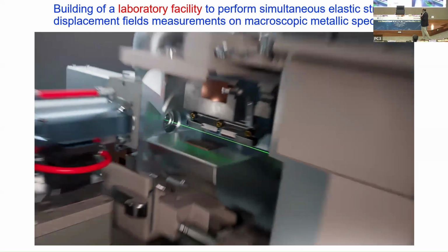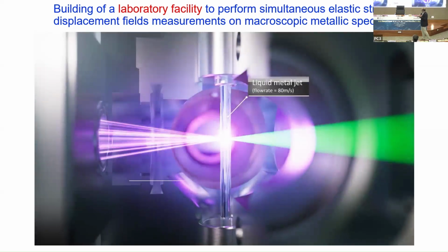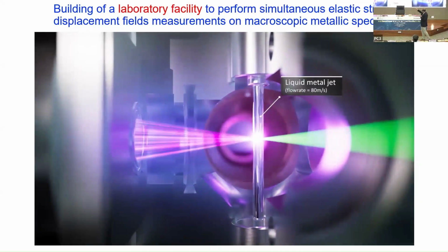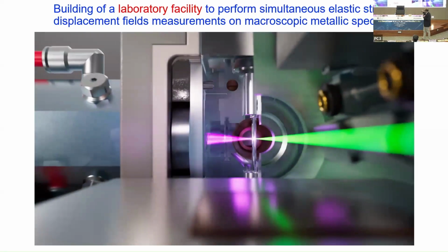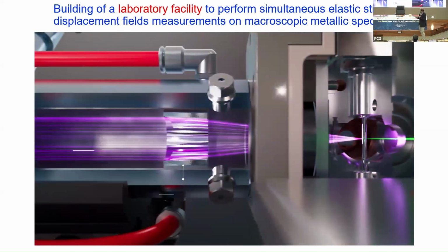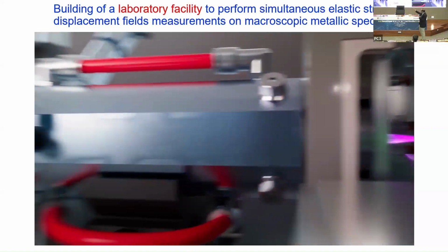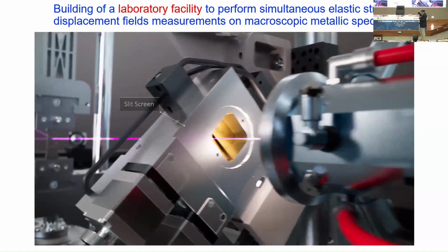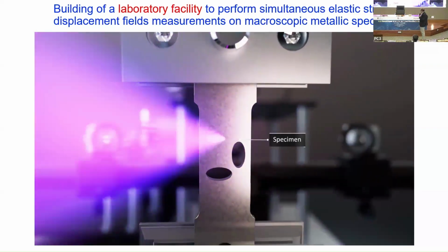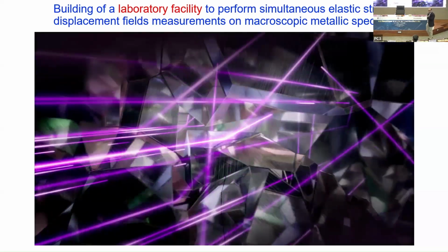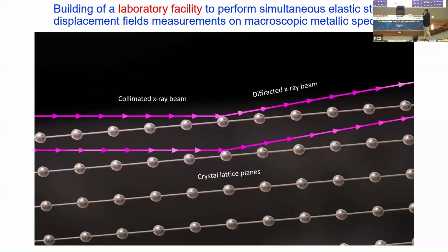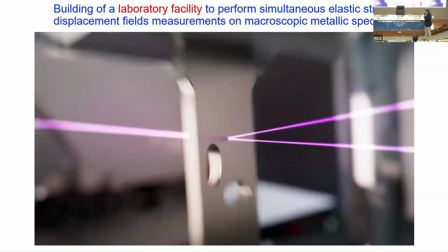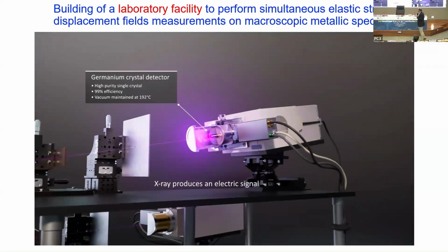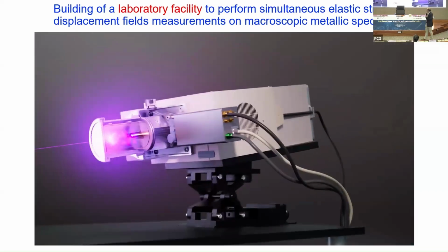That X-ray source comprises a liquid metal jet, indium in this case, approximately 80 meters per second. An electron beam comes and hits this liquid metal jet. You get X-rays emitted, but they are in a conical shape. You have to collimate it. And then you get these collimated beams, they go into this specimen. They will hit this specimen. The X-rays will diffract from all these crystals, which are these crystal planes that you're seeing here. And they go into these detectors. These are very high efficiency detectors. They've been cooled to a very significant level to reduce noise.